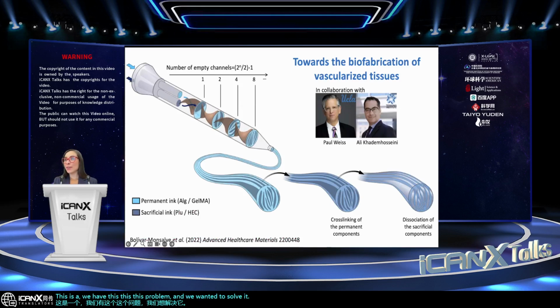And well, together with Professor Paul Weiss and Ali Khademhosseini, we came up with this idea of using also chaotic printing to make vessels, to make empty channels within our constructs. So it occurred to us to use a sacrificial material. So use a permanent material that is going to form the filament of hydrogel, and a sacrificial material that is going to remain liquid, and it's going to be removed from the construct, from the fiber, and it's going to leave empty channels that can work as blood capillaries.